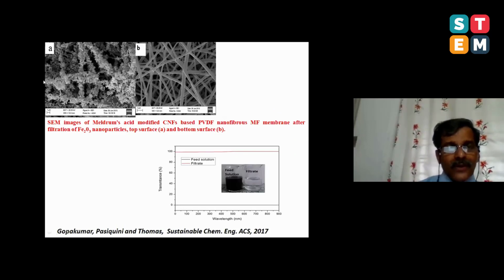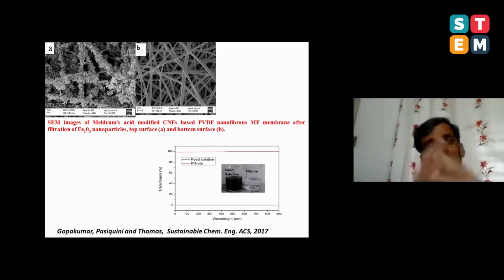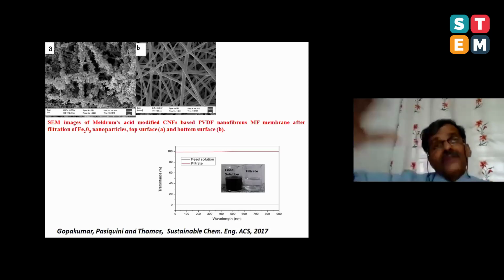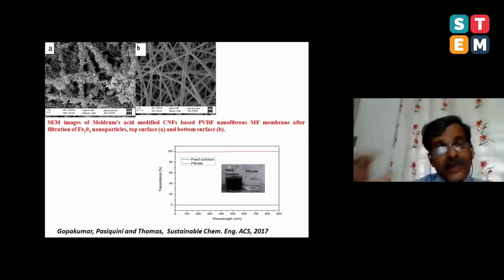Look at our filter modified with nanocellulose. See, the top of the filter is full of nanoparticles, suspended particles. So all the suspended particles could be separated. This is basically by a size exclusion principle, because the pore structure was so small after coating the nanocellulose, and this could retain all the suspended particles. Look at the bottom part of the filter. This is made of PVDF. Look at the feed solution, impure water. This is pure water. In the impure water, there is no transmission because these suspended particles scatter the light. And after the filtration process, look at this, you get very pure water.